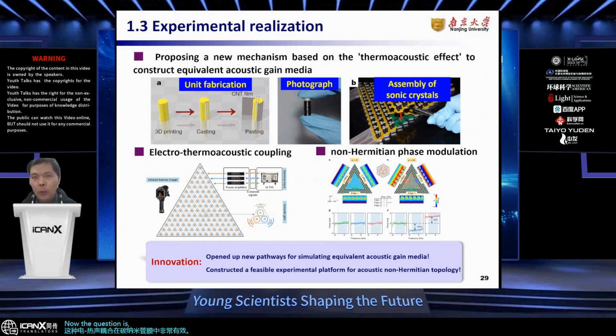Now, the question is, how do we combine CNT film with sonic crystals? We use 3-dimensional printing to create rods made of ABS plastic with 2 voids inside to cast the electrodes. These electrodes connect to the CNT films wrapped around the rods. We assemble several rods into a triangular lattice and mount it onto a PCB board.